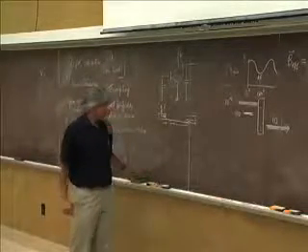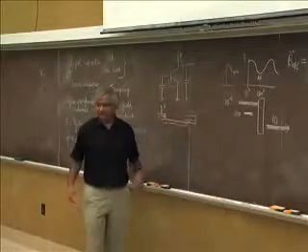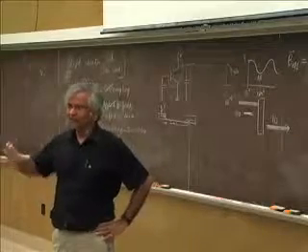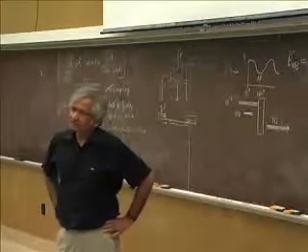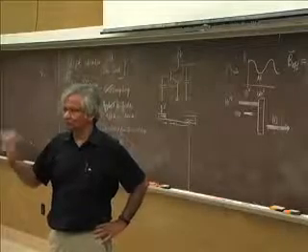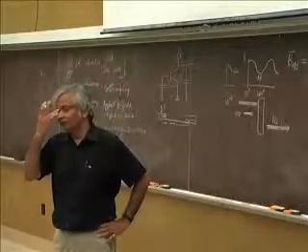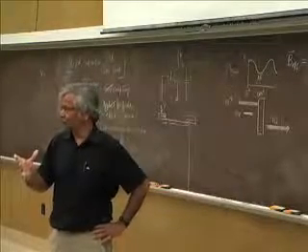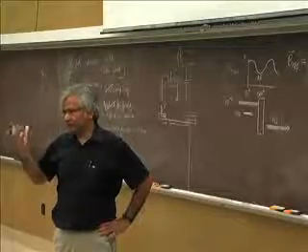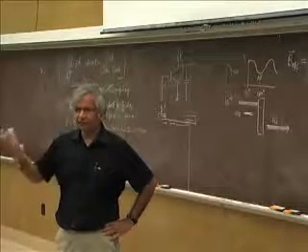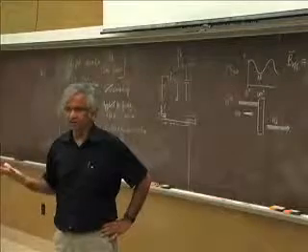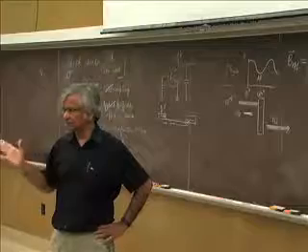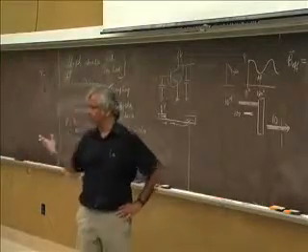So this is a very important development, but then you might say that, well, magnets are big things, it takes a long time to switch one of them. So wouldn't it be slow? And again, that is because our experience is with relatively big magnets, meaning ones that have millions of spins in them. Then it does take longer to switch. On the other hand, a magnet can be stable with even 1,000 spins in it. Those are things people have built. And then they can be switched a whole lot faster and with a whole lot less energy. But those are again things that need to be looked at to be sure.